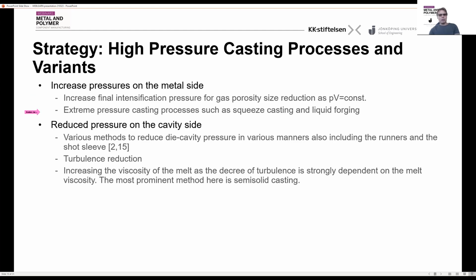And there are ways also where you use extreme pressures like squeeze casting and liquid forging. You can also work with reduced pressure on the cavity side. And here it's not really having a counter pressure, but more evacuating the chamber itself in order not to entrain gas during filling. But then again, there's a lot of work in order to control turbulence, and there's ways also to work with changing the viscosity of the melt that we will come to. You can take the next.